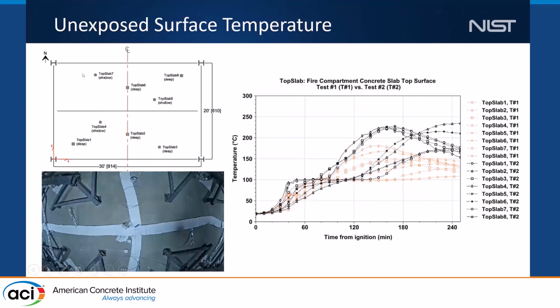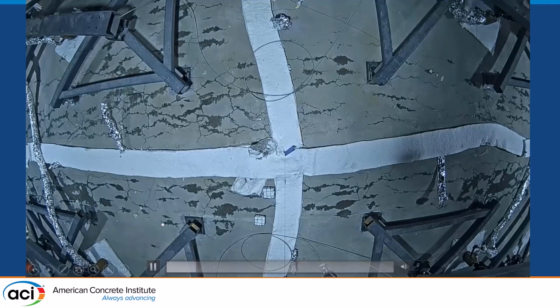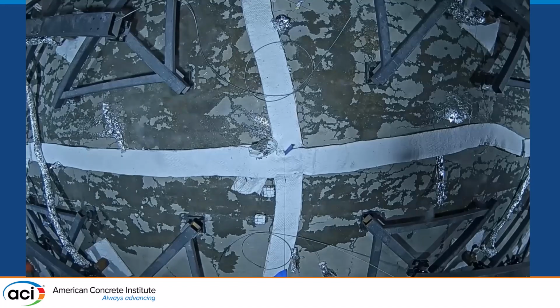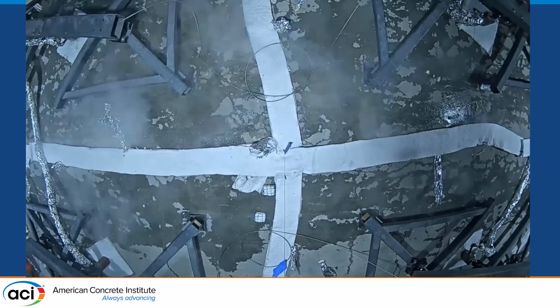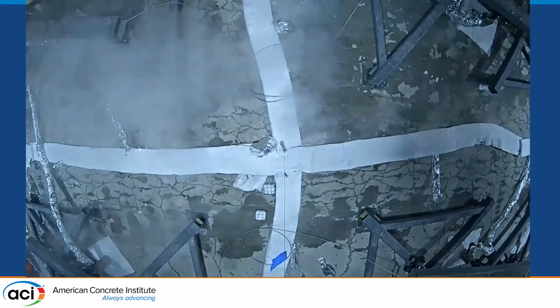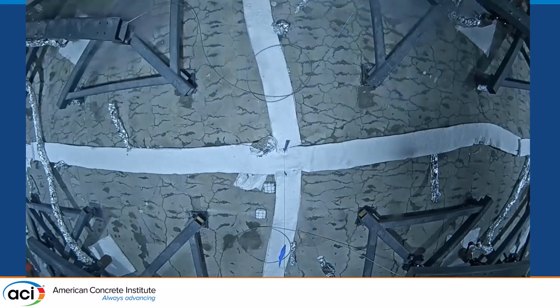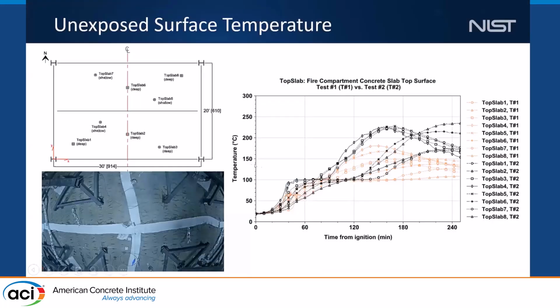We also mounted thermocouples on the top of the slab, basically to measure the unexposed floor temperature. And as you can see here, the top surface temperature is affected by the moisture driven out from the concrete during the early phase of the fire. But once the moisture content has dried out, the temperature started increasing. The top surface temperature was measured in the range of 180 to 230 degrees Celsius from test number 1 and 2.